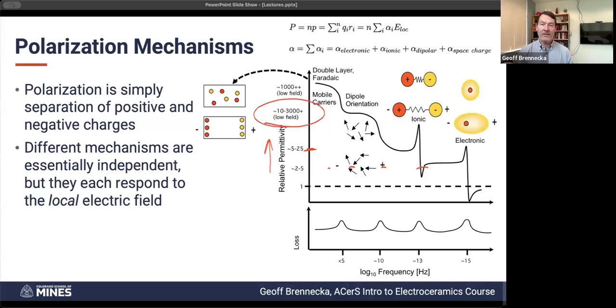So if you want something that has a very high permittivity, and if we go back to the capacitor model, high permittivity means high amount of charge that we can store, and high amount of energy that we can store, then you're going to have to take advantage of some of these other polarization mechanisms. So dipolar orientation is one of them. And then we get to even lower frequencies. And then we've got things like mobile carriers or Faradaic reactions like you have in a battery. There are a lot of different mechanisms that can contribute to relative permittivity down here.